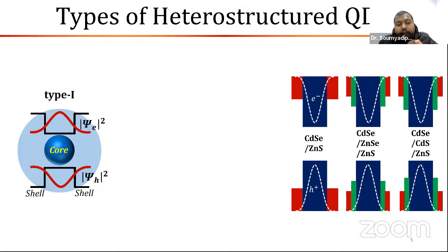Now, depending on the structure of the core-shell, quantum dots can be classified into 3 classes: type 1, type 2, and quasi-type 2. Now, what is type 1? In type 1, what do you do? We put a core quantum dot, and then we put a shell over it. Now, what is the band structure of the shell? This is very important. The band gap of the shell should be much more than the core.